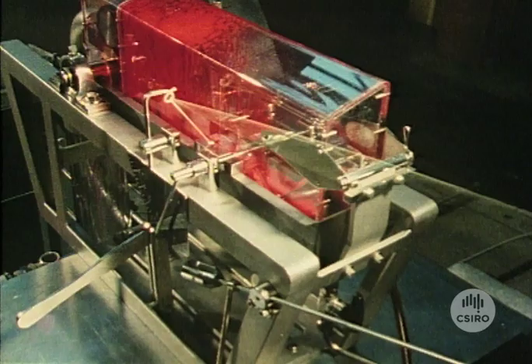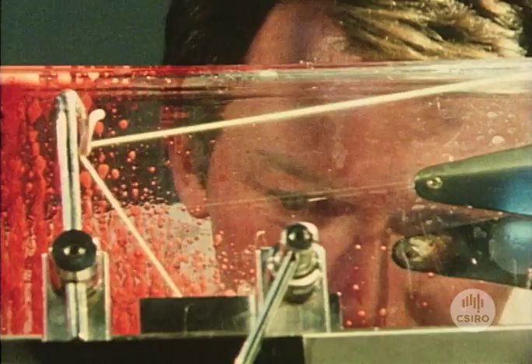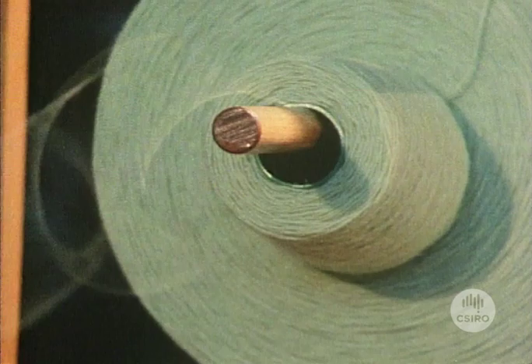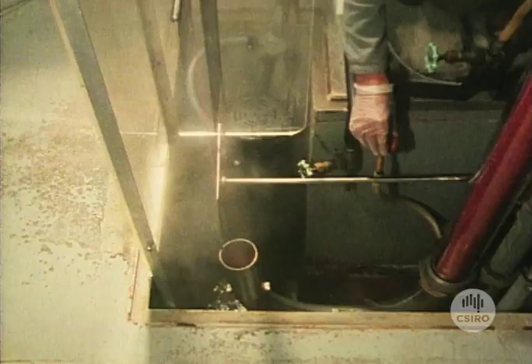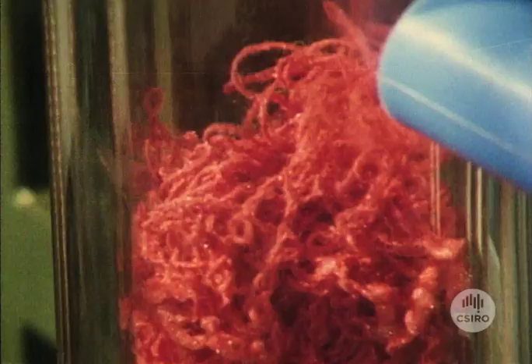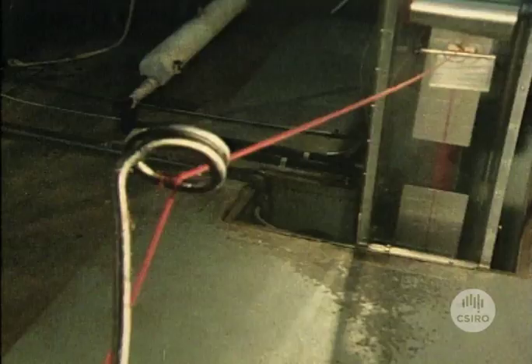The most difficult stage in the system is application of the dye — a stage which foiled previous attempts by German and French companies to develop continuous dyeing machines. The next stage is to fix the dye, which is done in a J-shaped tube where the yarn is steamed for about eight minutes. Inside the tube it looks like a nasty tangle of worms, but miraculously the dyed yarn can be drawn out and wound without trouble, ready for knitting.